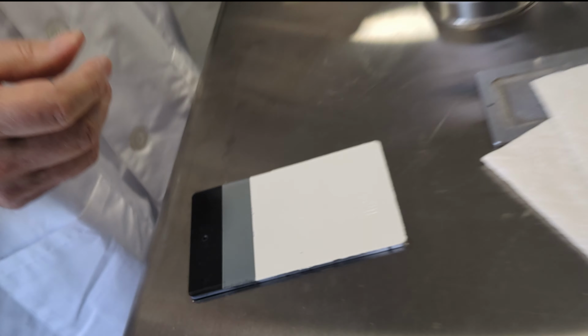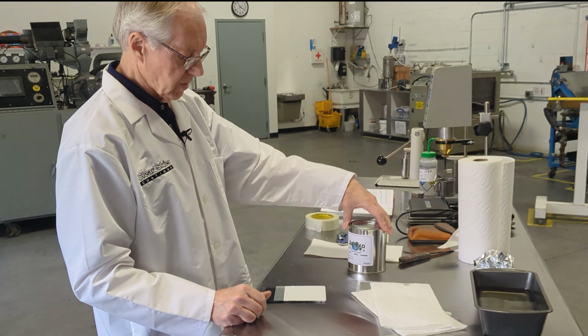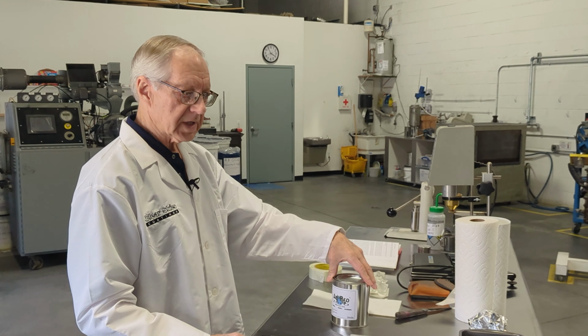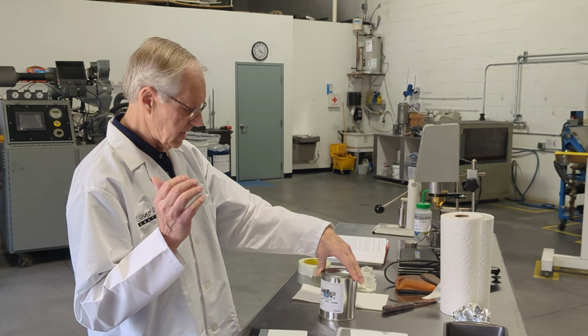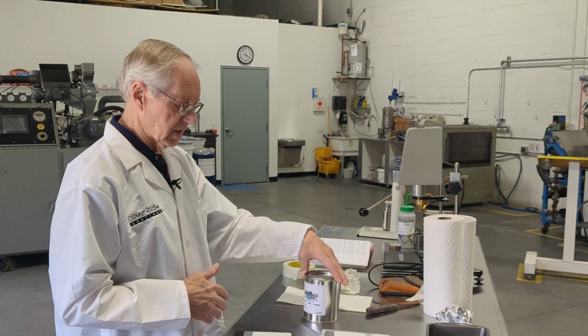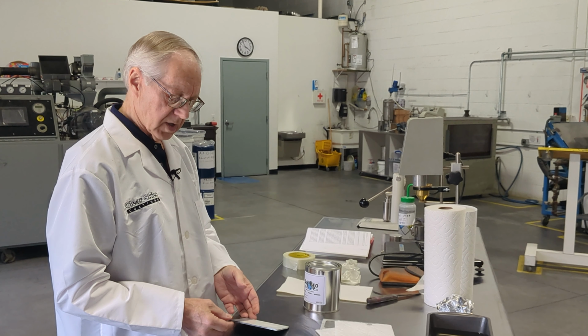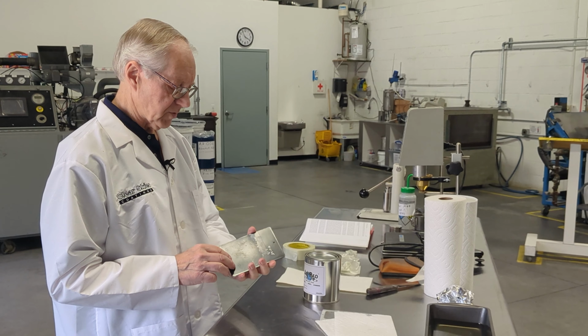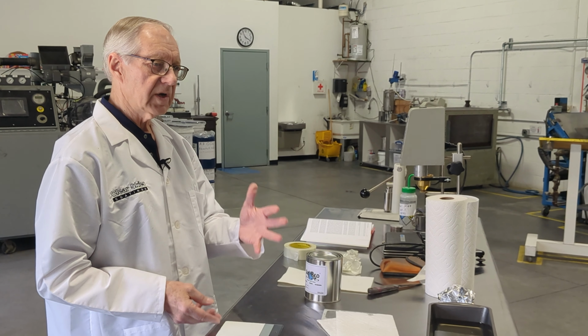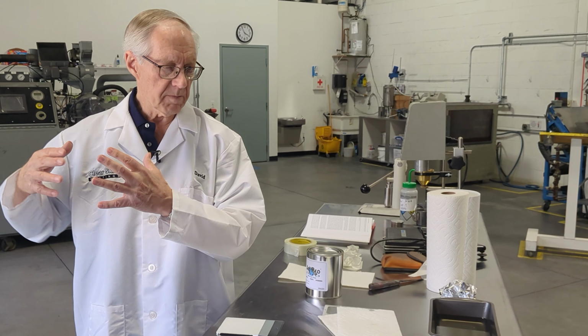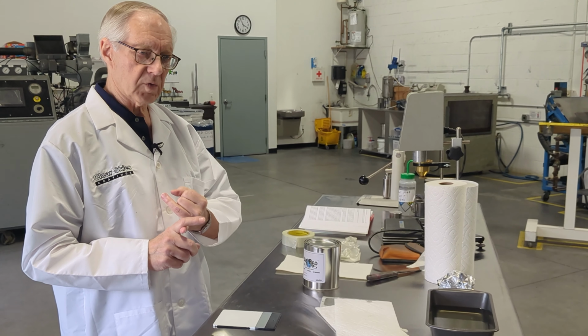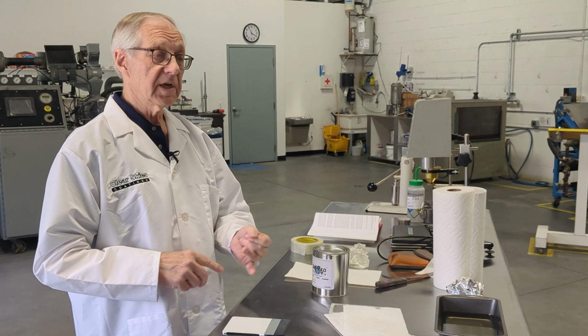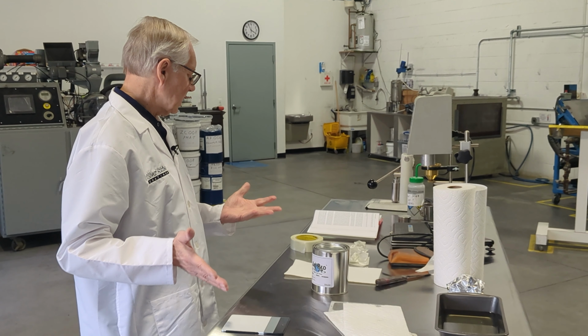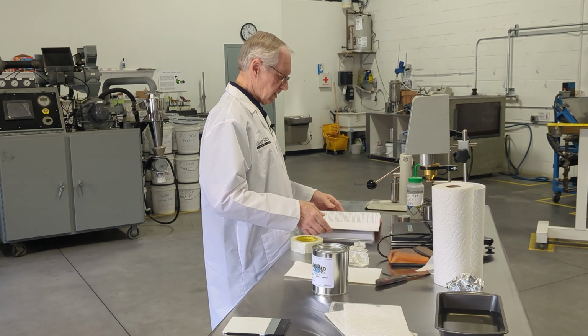So we've created this ultra-low cure adhesion promoter that has 0 VOCs, 0 HAPs, 0 halogens, no odor whatsoever. It resolves all of the environmental problems with the adhesion promoter, and you still have the adhesion promoter method that is the most robust, the most effective, and the most versatile. And this may be a real technical breakthrough.